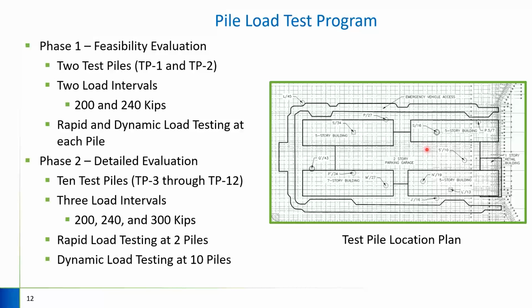So getting into the actual pile load testing program, we had a two-phase program since we did not know if this was going to be an economically feasible project. And so the first phase was just to determine whether or not these piles could potentially be reused. And because both the owner, who is Massport for this project, and the developer, Roseland, did not want to pour a significant amount of money into a load testing program, should the piles be beyond repair, it was determined that we do an initial program with 2 test piles that would consist of loads of 200 kips, which was the minimum financial feasibility for the project, and 240 kips that allowed us to gain some efficiencies and reduce the cost for both the owner and the developer.